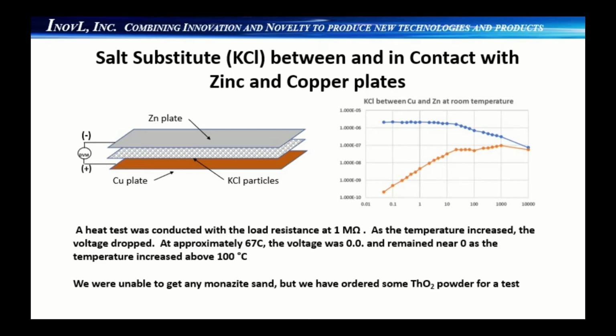Due to the fact that KCl is known to be hygroscopic, we conducted a test in a kiln where we increased the temperature. As the temperature increased, the voltage declined and was approximately zero at 67 degrees C, remaining there as temperature was increased above 100 degrees C. These results are consistent with the dehydration of KCl as temperatures increased.